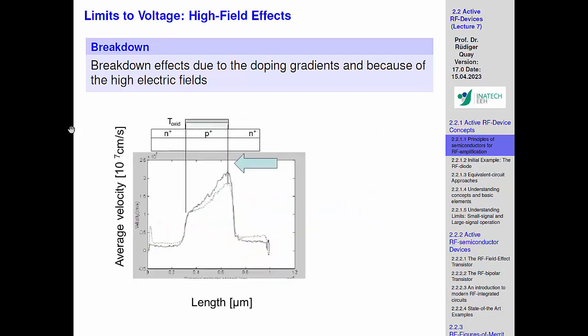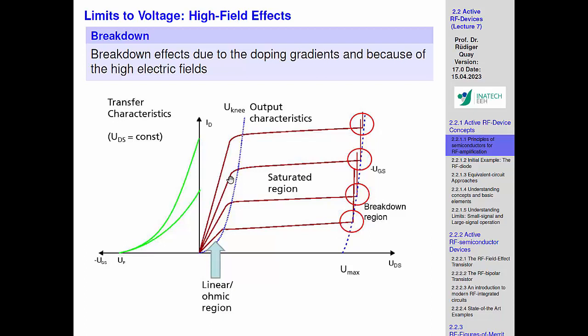And why does a breakdown occur? This is something which occurs not only in MOSFETs, but essentially in any device, but it's a high field effect, and that's something which we have depicted here. So when we look at the velocity, first of all, of the carriers going under a gate, then you see that they are very pronounced at the edges. Yeah, so it's not only this limit which I was talking about earlier. It's not just the breakdown field of the nitrides or of the oxides which are around the device. It is very much in the channel.